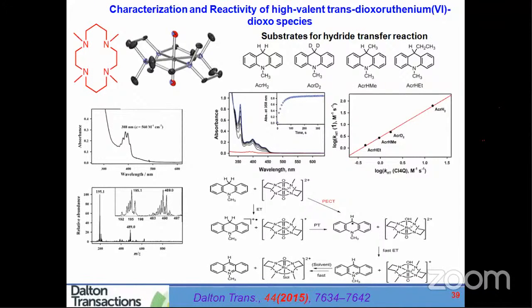Again, we did not leave the ruthenium dioxide species we prepared earlier. So we thought we will try something else with ruthenium dioxide. You can see this is the ligand. The structure we reported, and we published it in Dalton Transactions 2015. You can see the two oxygens are trans, characterized by UV-visible spectra and mass, right? And then we did reactions with acridine substrates as well as alkyl hydrocarbons.